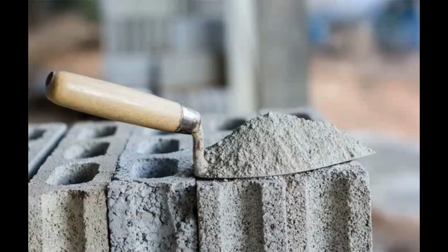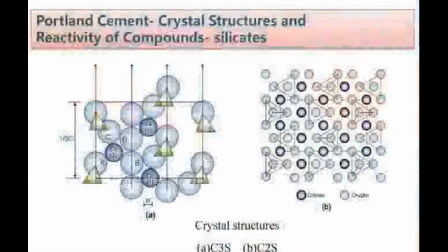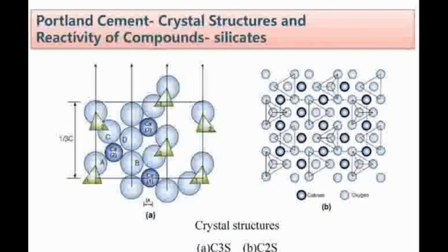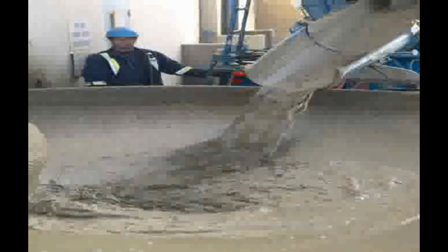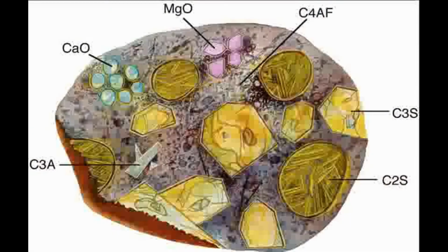About 90 to 95% of a Portland cement is comprised of the four main cement minerals, which are C3S, C2S, C3A, and C4AF, with the remainder consisting of calcium sulfate, alkali sulfates, unreacted free CaO, MgO, and other minor constituents left over from the clinkering and grinding steps.